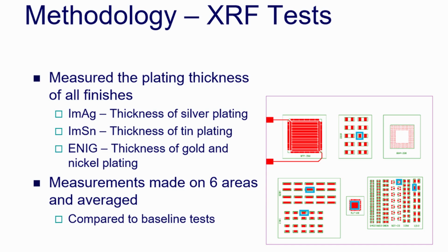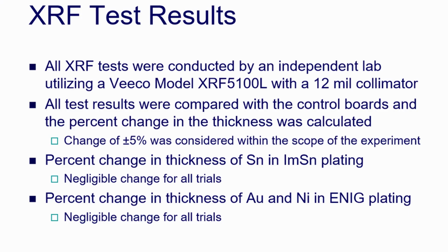The last analytical test that was conducted was X-ray fluorescence, or XRF, tests. This test measures the thickness of different plating materials. For immersion silver, it measures the thickness of the silver plating. For immersion tin, it measures the thickness of the tin plating. And for the ENIG plating, it measures the thickness of gold as well as the thickness of the nickel plating. It was found that for both immersion tin and ENIG, no significant changes in the thickness of the platings were noticed before and after cleaning, even after six cleaning passes. So this further proved that the plating materials were fully compatible with all four cleaning agents.